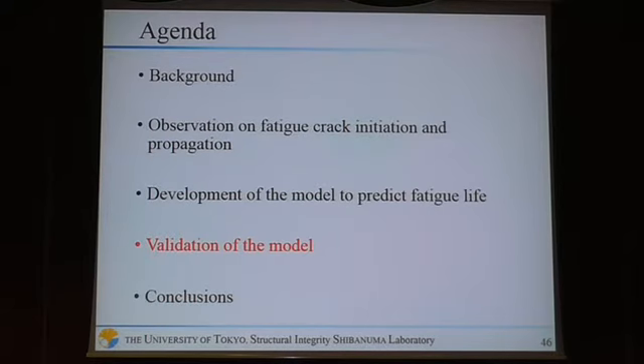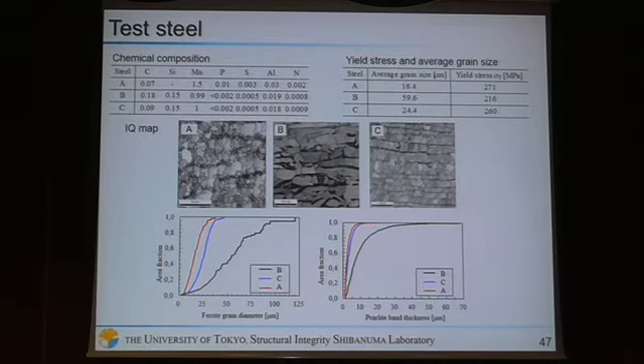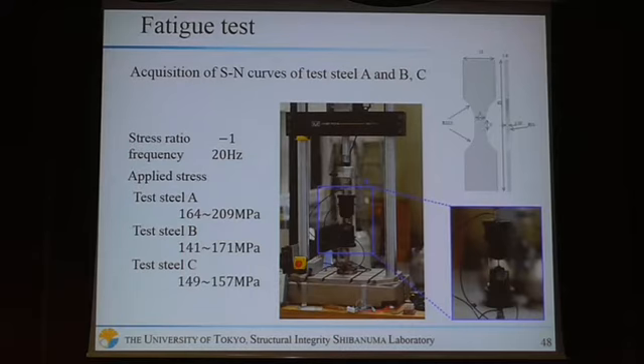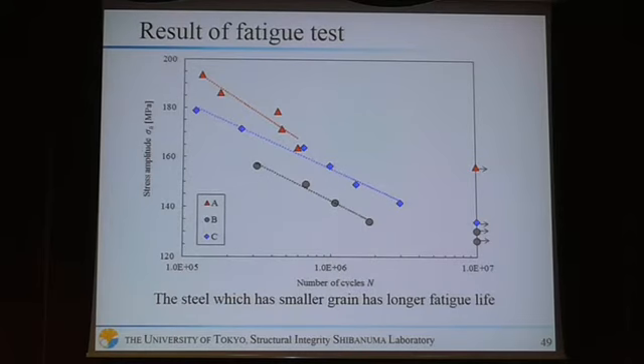Next, validation of the model. In the fatigue test, we used these test steels. For model validation, we conducted the fatigue test in this condition. This is the result of the fatigue test. The steel which has a smaller grain has longer fatigue life.